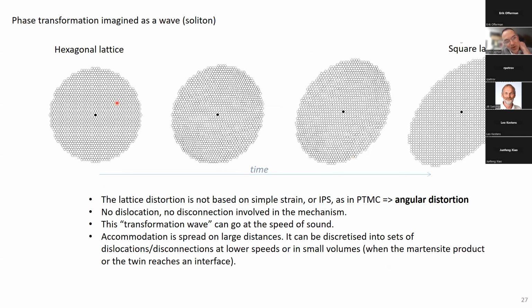For example, I take an example here. It's a hexagonal crystal, in 2D. It's a hexagonal stacking of atoms. And I can show you that I can go from here to a square stacking of atoms without dislocation. I just start to make a slight angular distortion here. It's nearly a square, not totally a square. Here it becomes a square, and progressively I go from hexagonal to square packing. And at the end, if I continue to propagate the wave of transformation, I get a fully square lattice. So try to find a very specific point defect or dislocation, you will not. Actually, this angular distortion is more connected to what I would call disclinations than dislocations, but that's too specific. So this is how I see a martensitic transformation.